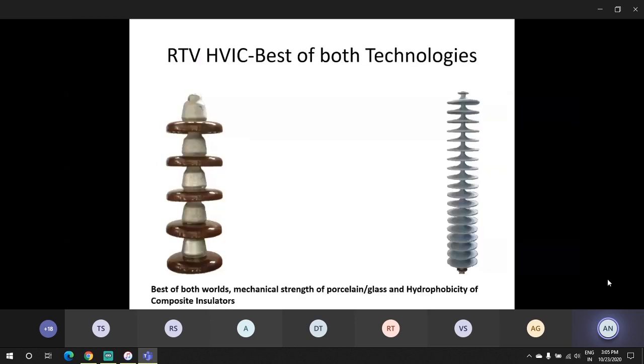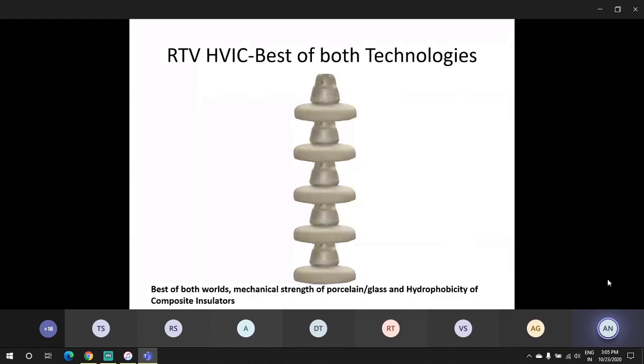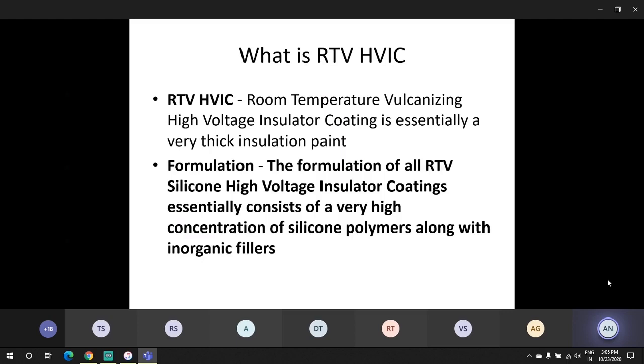If I make a pictorial representation, it is the best of both technologies. That means the silicone is coated over porcelain or glass insulators, and it gives you the mechanical integrity of the porcelain or glass and the hydrophobicity of composite insulators. What is RTV HVIC? It is basically a room temperature vulcanizing high voltage insulator coating. It is essentially a very thick insulation paint, and the formulation of RTV silicone coatings has a high concentration of silicone polymers along with some inorganic fillers.